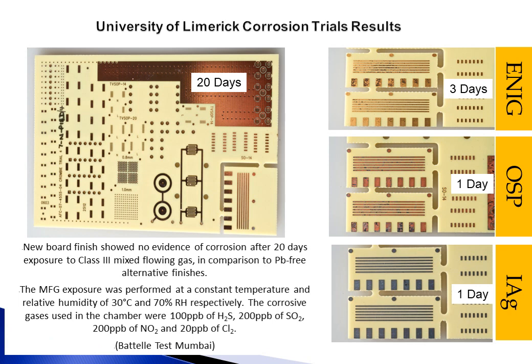This slide shows the results of the tests compared to ENIG, OSP and immersion silver. The immersion silver and OSP boards were both basically unsolderable after 1 day. The ENIG board managed to last for 3 days, whereas ours was still going strong at 20 days. This test is based on the Battelle specification for the environment in Mumbai.